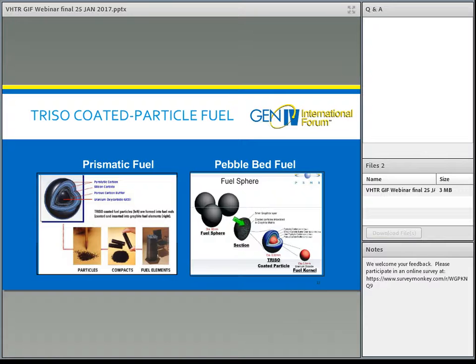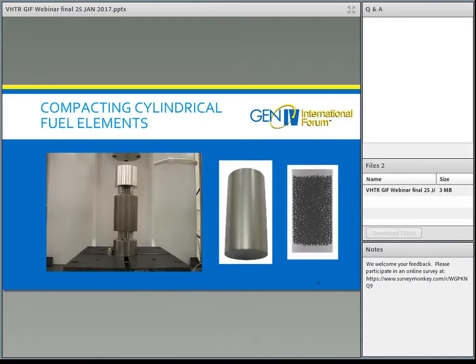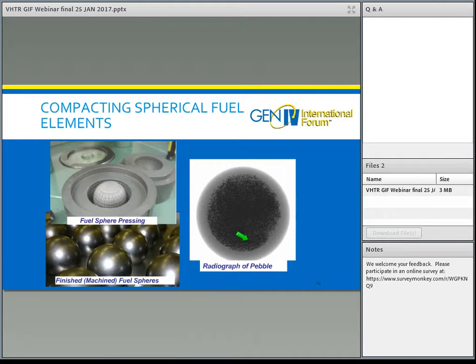In the center of the pebble there are the TRISO particles, and toward the outside is what they call a rind of graphite, an unfueled layer of graphite outside. Similarly, here is a radiograph of a pebble which shows the fuel portion in the center, and then the outer rind which does not contain fuel. Again, they are put into a press which presses the matrix and particles together into a solidified form, which is then baked and, in this case, finished and machined into very smooth cylindrical or spherical shapes that are used in the reactor.